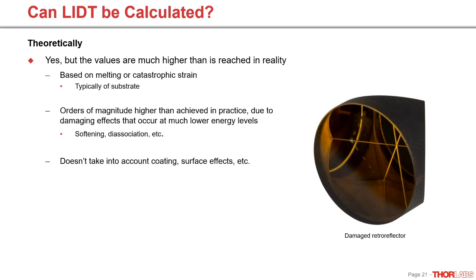Some of the numbers necessary to do these calculations are not necessarily easily obtained for your coating materials, because a lot of parameters are well established in the literature for bulk substrates, but for coating materials, your properties aren't necessarily going to be the same as the bulk. That can even vary run to run or chamber to chamber in one particular coating house. So even if you can find some of the values in the literature, they're not necessarily going to work for you. And of course, this doesn't take into account any surface effects or any of the defects involved. So you can't really calculate this theoretically.